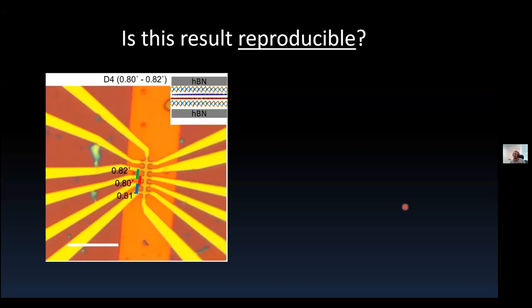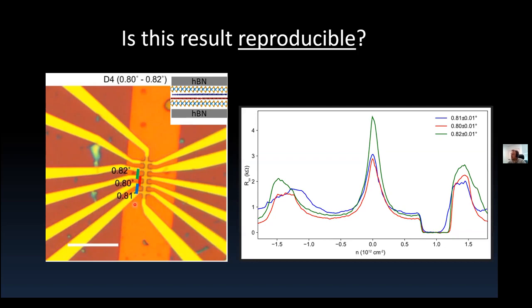So we had another device, this time slightly different, meaning that we put tungsten selenide on both sides. And we were a little bit lucky that this one showed three pairs of contacts all in this range around 0.8 degrees. So you can see it's not perfectly ordered, but the disorder here is very low. And now if you compare the line traces from all these devices, it all checks out. Basically, the charge neutrality is here, there is no real gap at full filling, and the superconducting pockets line up. So we checked that mark.